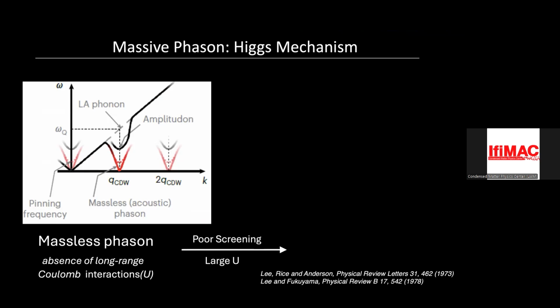However, this gapping that I'm talking about is not a full gap. The charge density wave usually connects only some pieces of the Fermi surface, and usually you only get a gap along those connections, and the rest of the Fermi surface remains intact. So if you start with a metal and go into the CDW phase, you'll get a tiny little gap, but the system remains metallic.